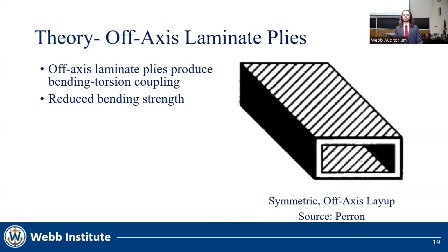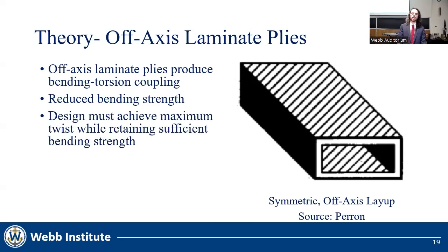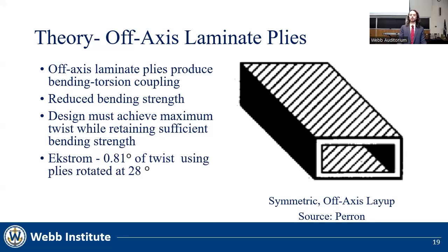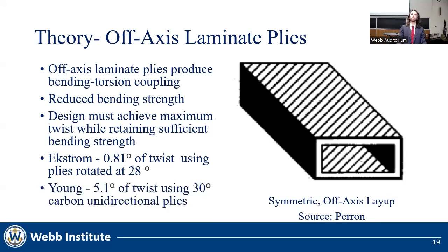Using equally angled plies on both sides of the beam produces the bending torsion coupling. Since the fibers are not aligned with the length of the beam, the bending strength is significantly reduced. Our design must achieve maximal twist while retaining bending strength. Higher twist angles will require thicker laminates. Ekstrom used off-axis plies to produce 0.8 degrees of twist in a 470 centerboard using plies rotated at 28 degrees. Professor Julie Young at the University of Michigan modeled and tested carbon fiber high aspect foils with a 30-degree ply angle. In the flow channel, they achieved up to 5.1 degrees of twist with their model.